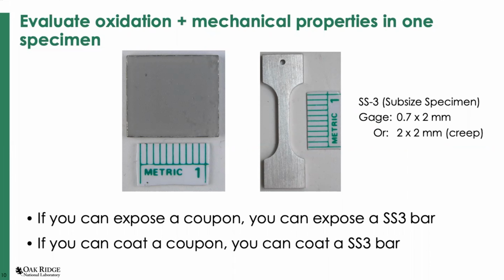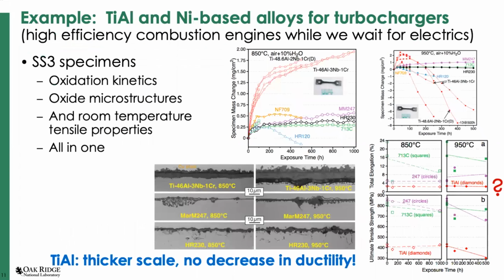And we've made different versions of this, increasing the gauge, the depth, thickness. So we get a 2x2 gauge for doing creep testing on some of these. And you can look through the literature and find examples where we've reported things like that in the past. I'll just give you a couple examples real quick. Again, this notion that you can do everything you want with a tensile specimen that you can do with a coupon. So here's a study where we're looking at turbochargers. Again, you might think this is a little bit outdated, but there is interest in high efficiency combustion engines while we wait for electric vehicles to take over.